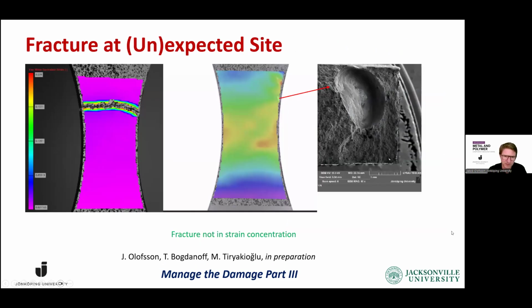But when we proceed to the fracture, it does not happen where we see the highest strain, because it actually goes higher up. And there you can see we have this indication of porosity also from the X-ray, but as you can see on the SEM picture there to the right, the pore was actually on the other side, but we are not looking. So we didn't see the high strain concentration on our side, but we could see the effect of it. But it didn't look as bad as the other ones that we saw on the front.